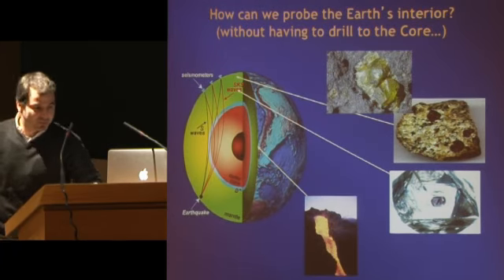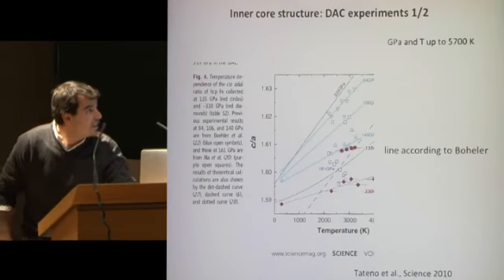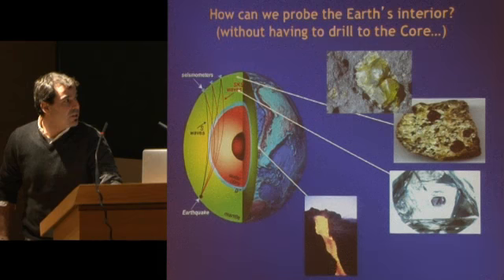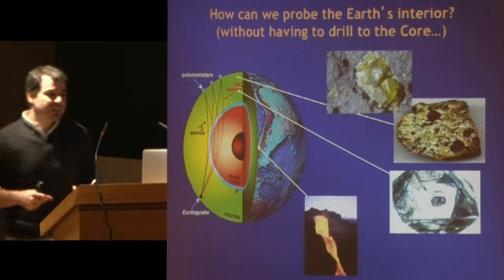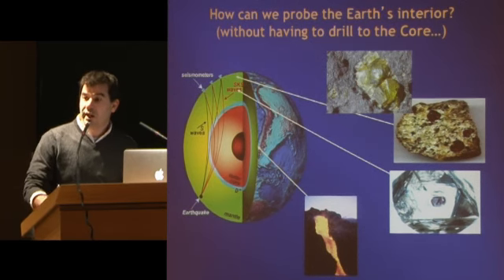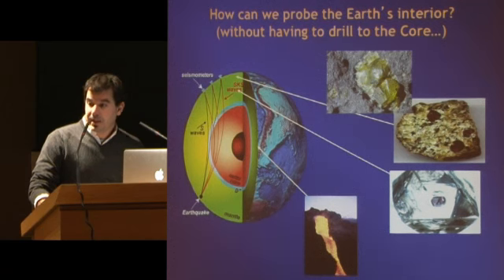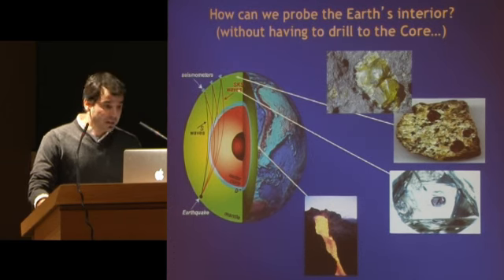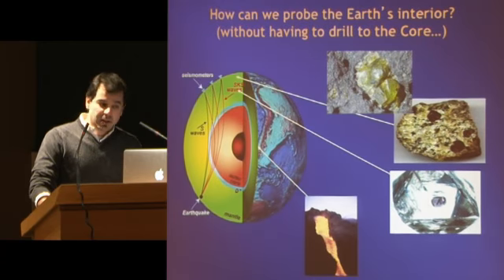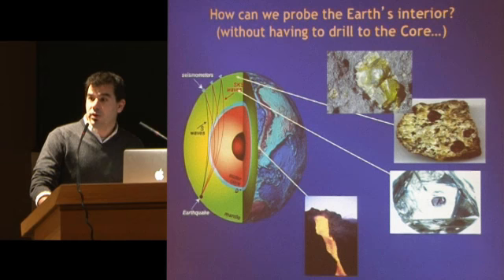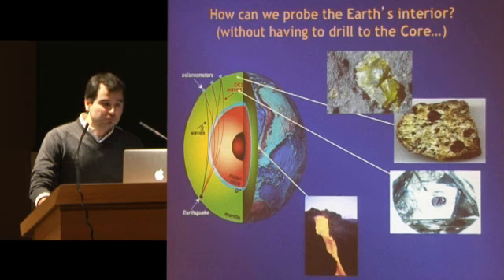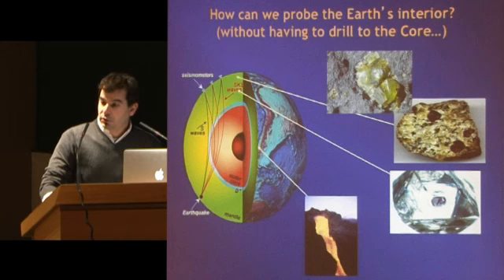Anyhow, the message of the previous slide that didn't come well was just to say that from an experimental point of view, now there is compelling evidence that the stable phase for pure iron at the condition of the Earth's inner core is hcp. And there is an increasing number of diamond anvil cell X-ray diffraction experiments that suggest that even inclusion of silicon and nickel up to reasonable amounts doesn't change this conclusion. From an experimental mineral physics point of view, the hcp phase of iron is the one expected stable. So in the following, I will just discuss sound velocity on hcp phases.